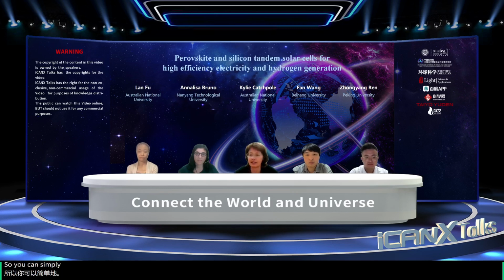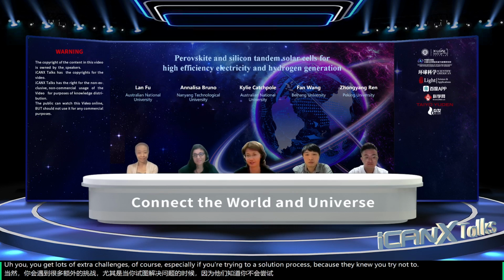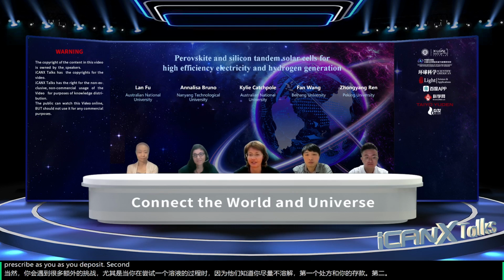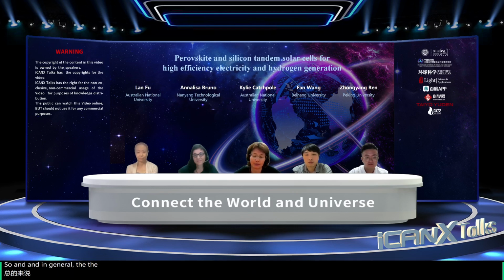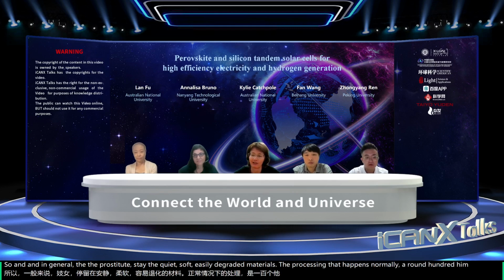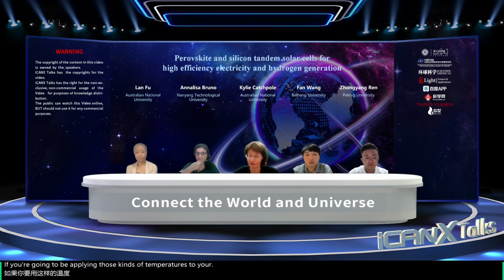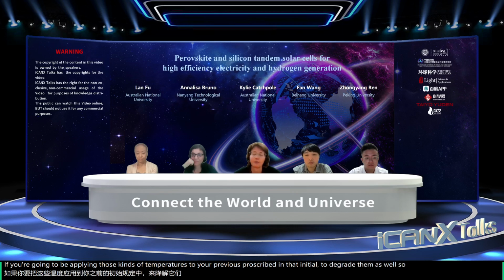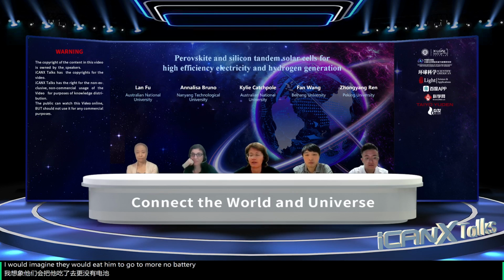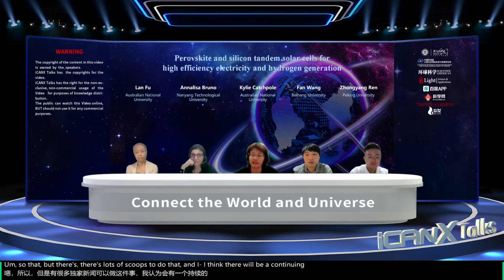So you can certainly do that, and people are already making all-perovskite tandems. So you can put a perovskite on top of a perovskite, with different band gaps. You get lots of extra challenges, of course, especially if you're trying to solution process, because then you try not to dissolve the first perovskite as you deposit the second perovskite. So in general, the perovskites are quite soft, easily degraded materials. The processing normally happens at around 110 degrees or so. If you're applying those kinds of temperatures to your previous perovskite, then there's potential to degrade them as well. So I would imagine you tend to go to more evaporation type methods in order to do that. Evaporation is normally a nice gentle thing to do. But there's lots of scope to do that, and I think there will be a continuing drive in that direction.